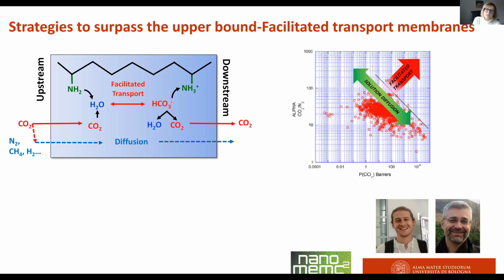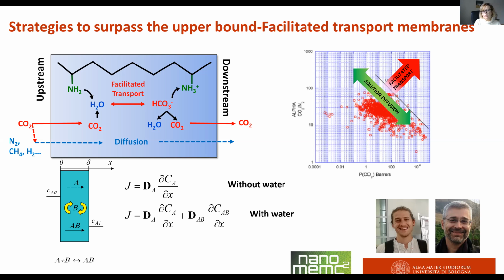Another example that I promised you to show was the example of the facilitated transport membranes. And as I anticipated, in this case, besides diffusion, you have a chemical reaction that takes place between CO2, the water that is present in the environment, which is humidified, and aminic groups present in the membrane. There is the formation of an ion which diffuses fast and which boosts the permeation of CO2 with respect to the permeation of all other gases. This mechanism allows to surpass the upper bound observed by Robeson, and so it is very much studied, and it is actually under study now for CO2 capture processes.